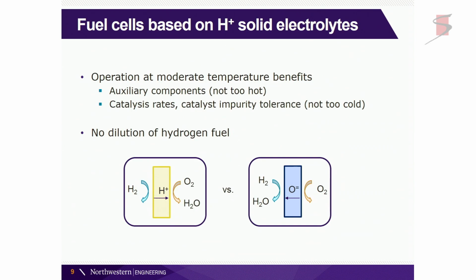Okay, so now why would we want a fuel cell that's based on a proton conductor as opposed to the other high temperature systems which are oxygen ion conducting? Well, it's been recognized, first of all, I already pointed out to you that the temperature is lower than in the case of the oxygen ion conducting systems, which is around 800 degrees Celsius. And that is not so low, because it's still high enough that the catalysis rates are high, and we have good impurity tolerance, so we don't have to clean up our fuel as much as we would, for example, in a PEM fuel cell.